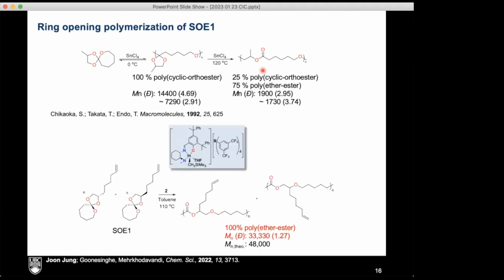species. In the case of Joon, what he was able to show is that this whole thing goes 100% to the polymer. And again, I show you both of them because we start with a mixture of diastereomers, so we're going to get a mixture of different products in terms of the regiochemistry, but that's irrelevant because at the end of the day, we have a polyester, polyether material with relatively high molecular weight. And since then, and this is not in the paper, we have systems that can go up to more than 100,000 grams per mole.